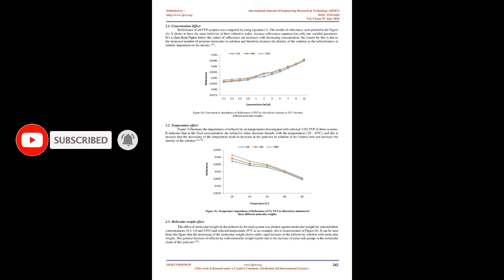2.3 Refractive index measurements. The refractive index measurements were carried out using a refractometer, type Kruss, Germany. The temperatures of measured solutions were controlled within 0.5 degrees Celsius. The refractometer was checked with the standard material monobromonaphthalene.